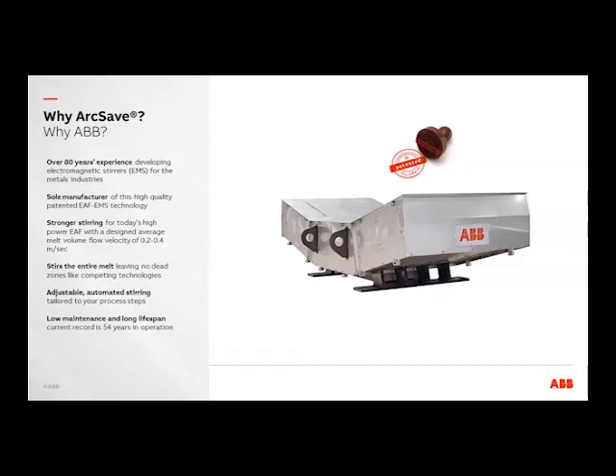The stirring profile is fully adjustable, 0 to 100%, and has an automatic stirring profile, which can easily be adapted to the level 2 system of the customers. We can then also adapt it for different scrap sizes, scrap types, alloy types, or different steel grades. We have very low maintenance and a long lifespan of the coil. To give an example, in Uddeholm in Sweden we have a stirrer coil which has been in operation for over 50 years. But in the unlikely event that you need to remove the stirrer due to a fault, it's fully possible to remove the EMS and continue to run the electric arc furnace independently of the coil.